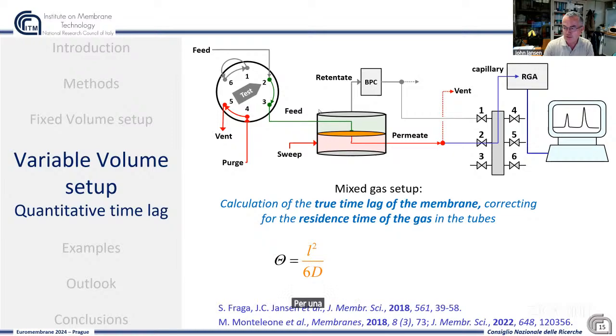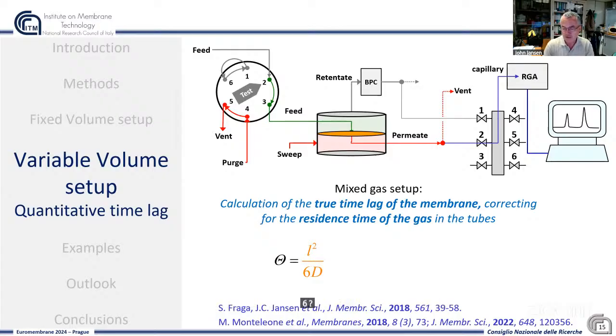around this membrane cell that you see in the middle is a vacuum system where you put vacuum on both sides of the membrane. Then at a certain moment, you expose the membrane to a gas, a single gas, which is one of the limits of the traditional system. Then at the other side, you look, as soon as you expose the membrane to the gas, at what's happening with the pressure.